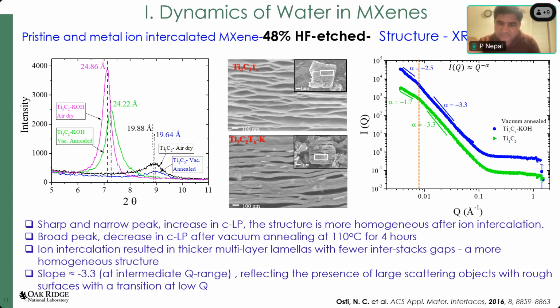Within that small range, suppose you are only focusing on your small angle neutron data, let's say within 0.01, I know you are not showing it here, but have you ever realized or remembered what the variation between minimum and maximum would be? I know it depends upon the sample, but normally maybe between 2 and 3. One thing is that for small angle neutron scattering, you cannot stay at a particular Q and collect the data. You have to have a certain Q range, and then that's the ensemble average.